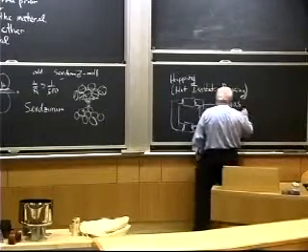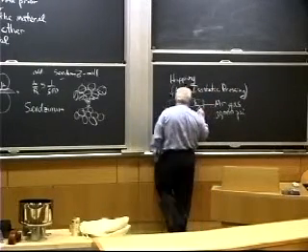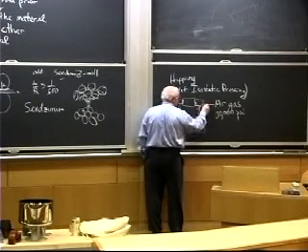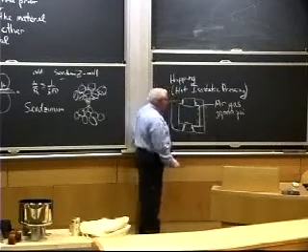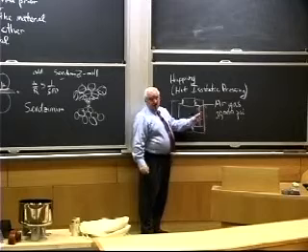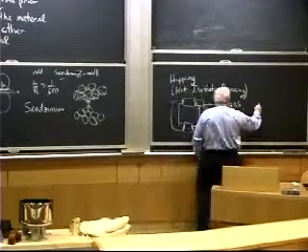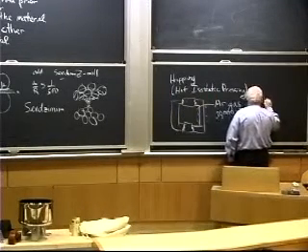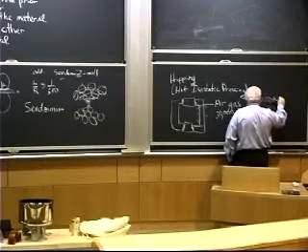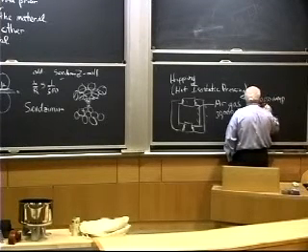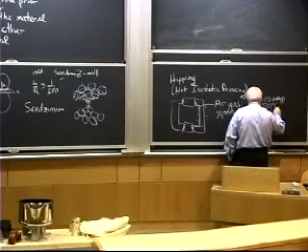But you put the whole thing in, and you either heat it internally with heating coils in here, which means you have to have electrical feed-throughs, or you heat it externally, in which case your pressure vessel has to be able to take the temperatures. But the one we had would go to 2,000 atmospheres, which is 30,000 psi, and about 2,000 degrees centigrade if we use the graphite furnace.